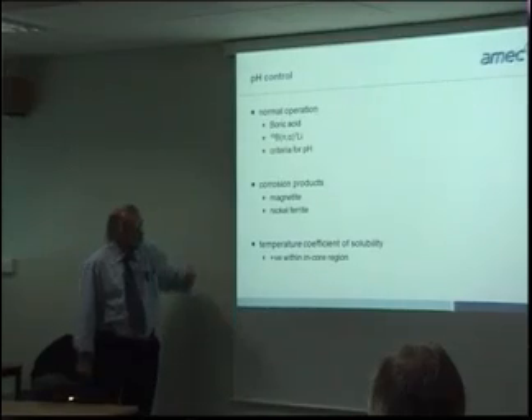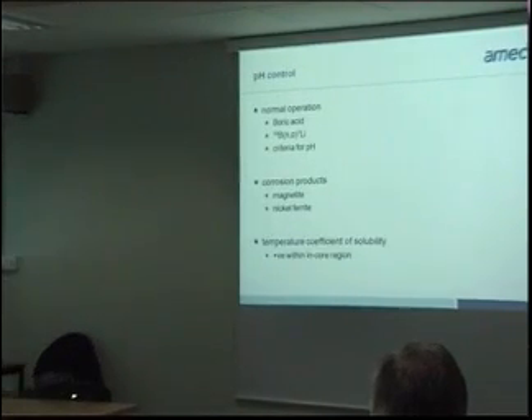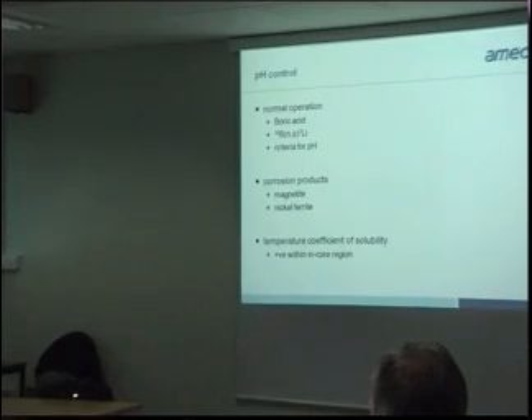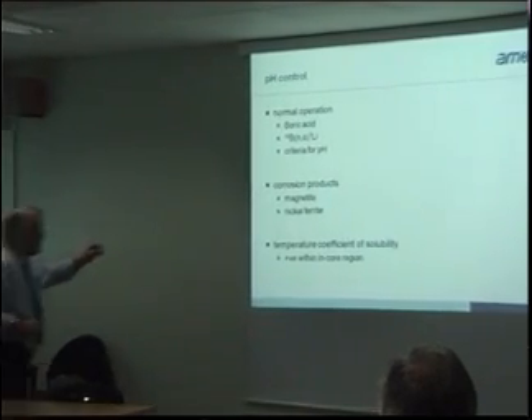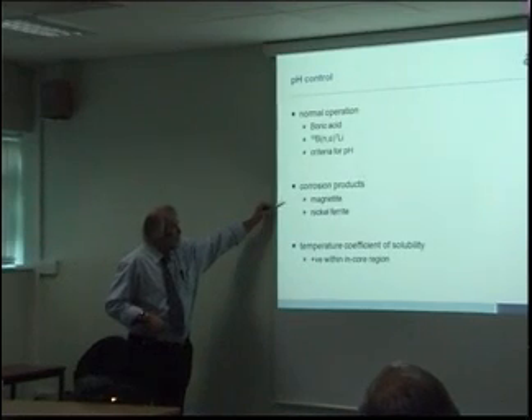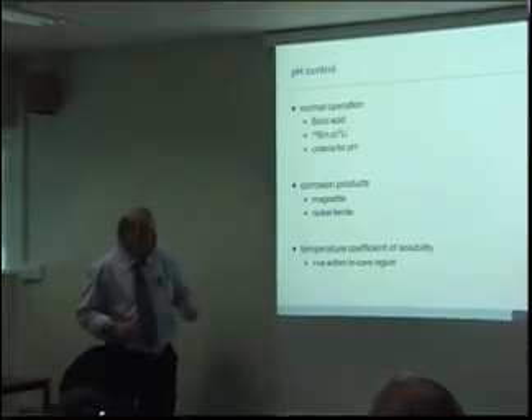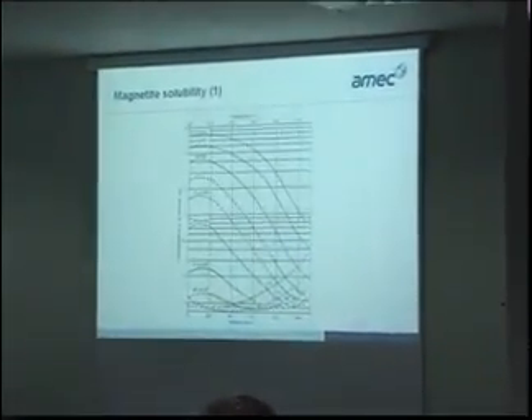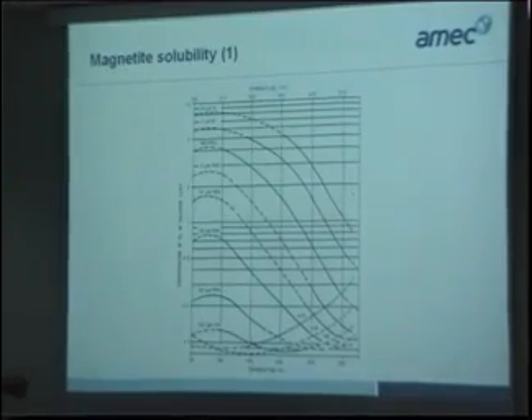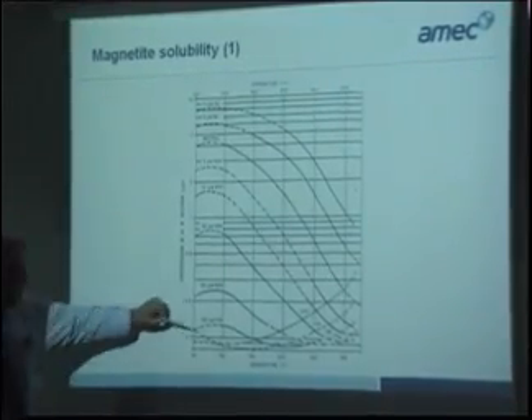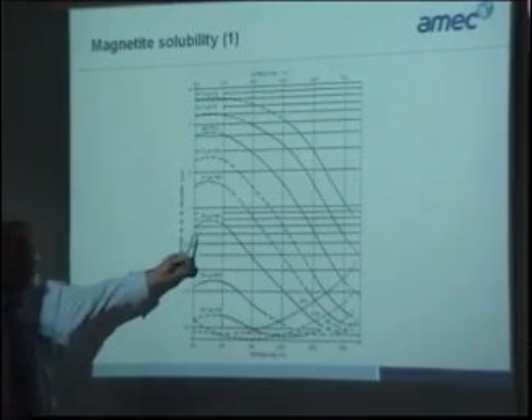Now the criteria for the pH really depends on the solubility of the corrosion products. We're going to have a look at that at the moment. Early experiments were carried out on magnetite, looking at the solubility of magnetite as a function of pH and temperature. Let's just look at the next slide, and you can see it's certainly not a linear situation. This is temperature along here, and each one of these lines represents a different pH, and it's written in terms of micromoles of potassium hydroxide. That's how the experiment was done.